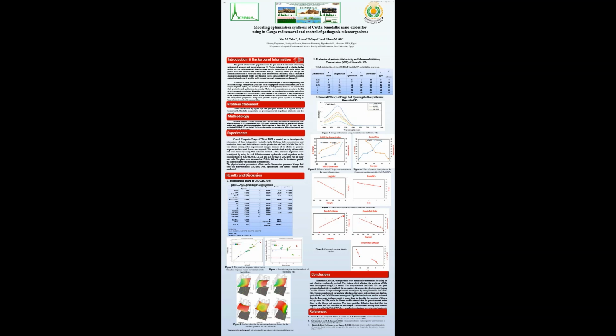Results and discussion. 1. Biosynthesis of CuO/ZnO bimetallic nanoparticles occurred by using the extract of fungus Fusarium oxysporum. The optimal conditions for synthesis of bimetallic CuO/ZnO NPs were pH, shaking, salt concentration and incubation time, with recorded values of 7, 140 rpm, 5 mM and 48 h respectively. The results were analyzed by one-way ANOVA to evaluate statistical significance for each factor.